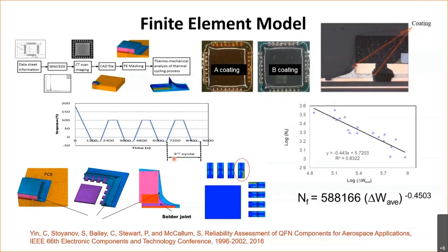A lot of accelerated life testing was done on these components, and with that data together with the finite element simulations, you could start building a lifetime model, number of cycles to failure as a function of plastic work. So the plastic work is the calculation from the finite element calculation, and then that's correlated with experimental data. So the log Nf here is from accelerated life testing, the log W is from the finite element calculations.